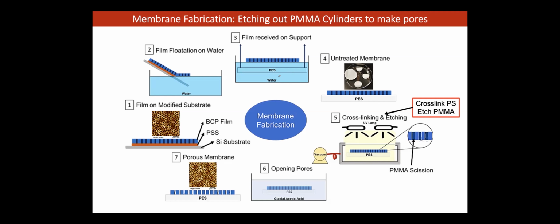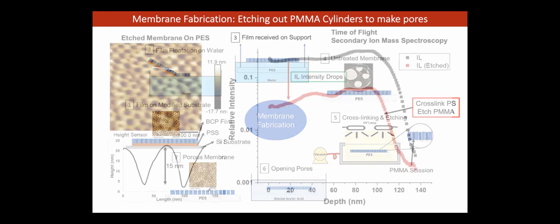Here we are making these membranes. You can see 1 through 7. We have a sulfonated polystyrene layer that allows us to cast the block copolymer film, float it on water, pick it up with the macroporous substrate, polyether sulfone, on step 4. And now we have this vertical order, but then we do the Tom Russell trick of etching with UV and cross-linking and dipping it into acetic acid to remove the etched material. And lo and behold, we get the nanoporous block copolymer, which is really thin, 50 nanometer on a macroporous PES, could be a couple of microns. And that's your membrane, and then you test it out.